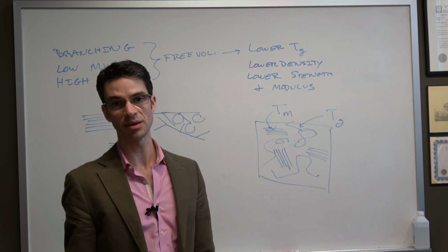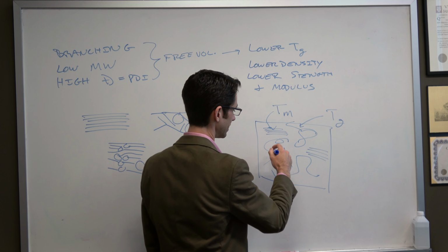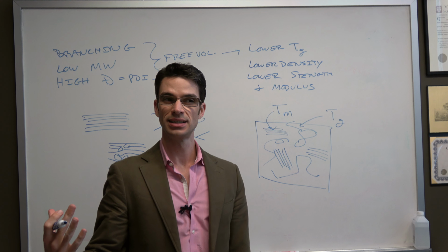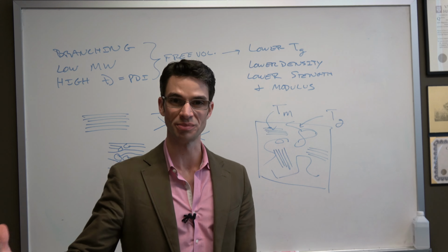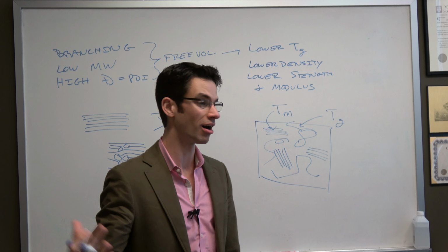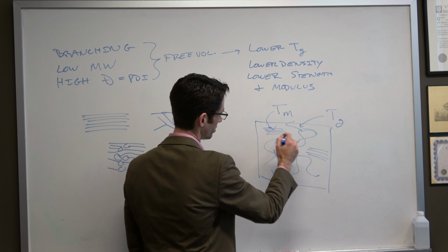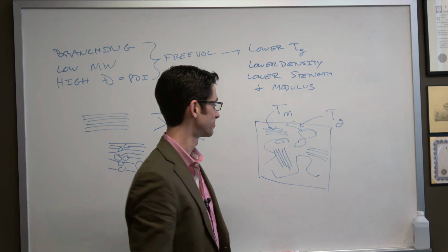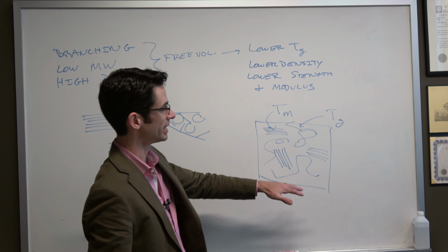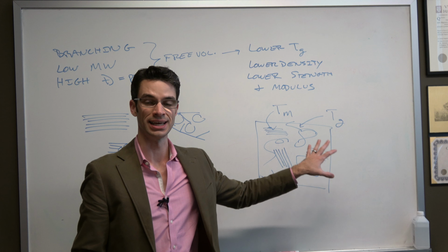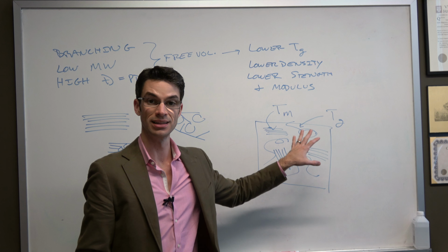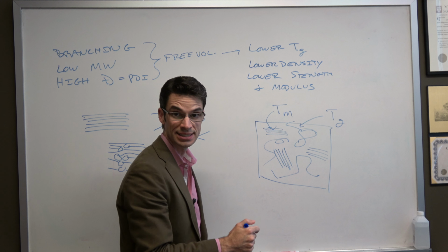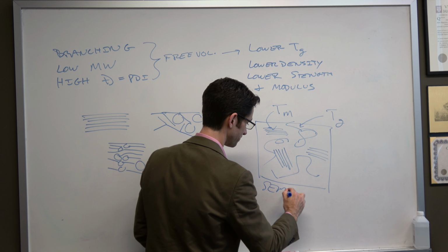The glass transition temperature is when the amorphous domains kind of melt, but it's not called melting. It's when they become soft. But when the crystalline domains are raised above their Tm, then they melt. So above Tg and Tm, this whole thing is just a viscous liquid. In order to have crystallites, so this is semicrystalline.